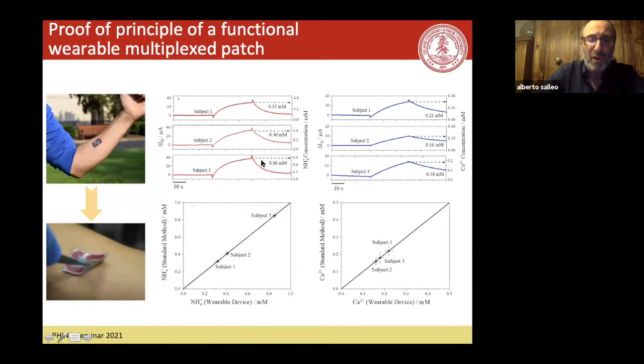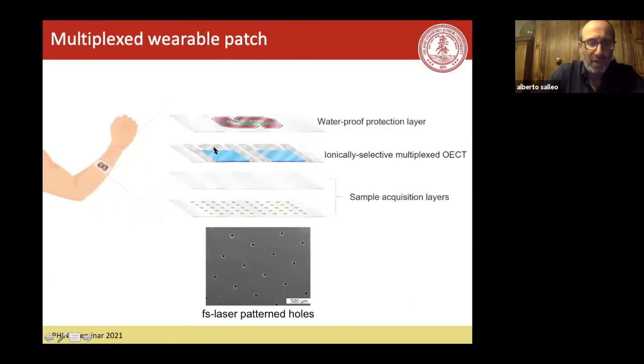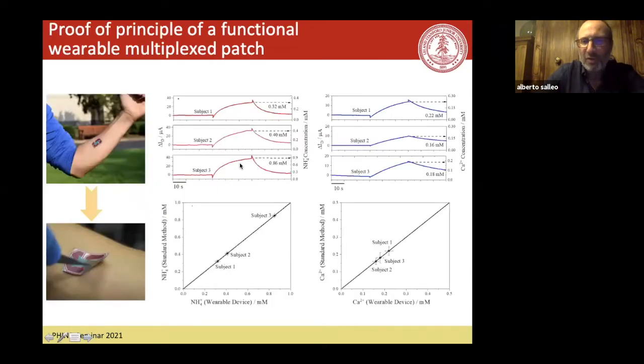It takes 30 seconds for the signal to build up because these devices are very large. These are not made by any microfabrication technique. Because they're large, it takes a lot of time for them to charge up with ions. They have a big capacitance, so it takes a long time, and that's why it takes 30 seconds. But this is not an intrinsic limitation of the device.